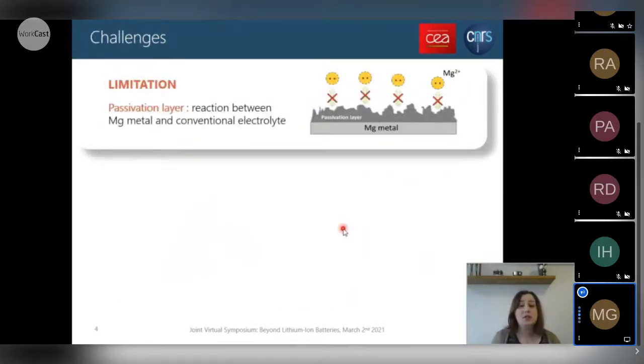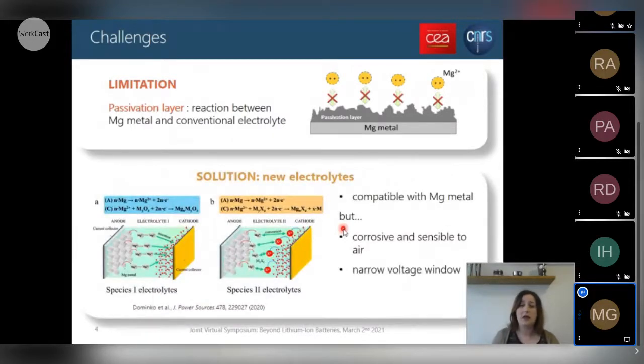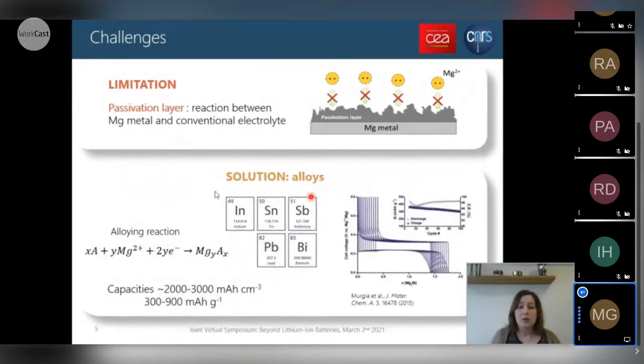So to solve this issue, 2 main strategies can be envisioned. The first one is to develop and design new electrolyte solutions. I will not enter into the detail of this here, but we recently reviewed this with Robert Dominko, Vito Di Noto, and Romain Berthelot. Basically, there are some electrolyte solutions that are compatible with magnesium metal. They do not form any passivation layer, but the problem is that they are often corrosive and sensitive to air, and they present a quite narrow voltage window. Another solution is to use p-block elements to replace the magnesium metal electrode.